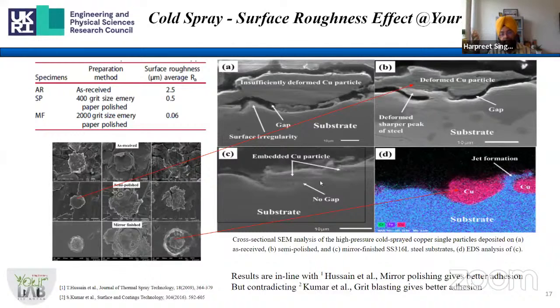We could see that our mirror polished samples were giving us very nice adherence. In fact, this is a point of quite some discussion in the literature. Some studies show that rougher surfaces are better for good adherence. Some others say polished samples are better. But when we investigated, we were more towards Hussain's group's argument that mirror polishing gives good adherence. We did this study with single particle impact as well. My student worked out a lot of details on why there was good adherence.